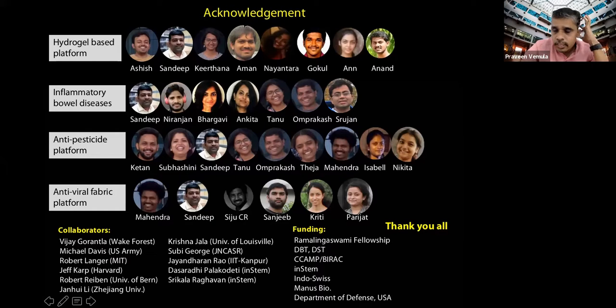Well, I think it's a pretty general process. There are 2 types of hydrogels known, right? One is polymer-based hydrogels. Typically, polymer-based hydrogels you can make through either covalent cross-linking or ionic cross-linking, or some of them form through a simple swelling process. But we primarily work on self-assembled hydrogels, meaning you take a single molecule, and when you put it in the solvent, they use intermolecular interactions: hydrogen bonding, van der Waals interactions, pi-pi interactions. We systematically incorporate these into the molecule, so that millions of molecules come together and form hierarchical structures, right? That's how they form nanostructures, micron structures and bulk gels.